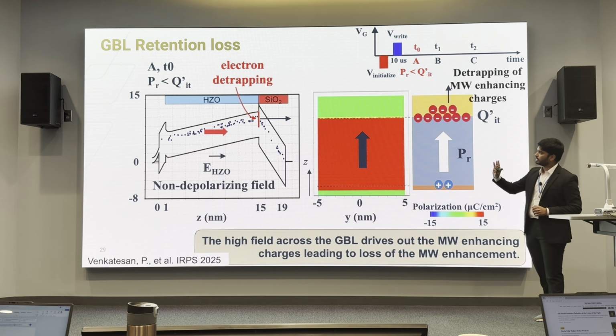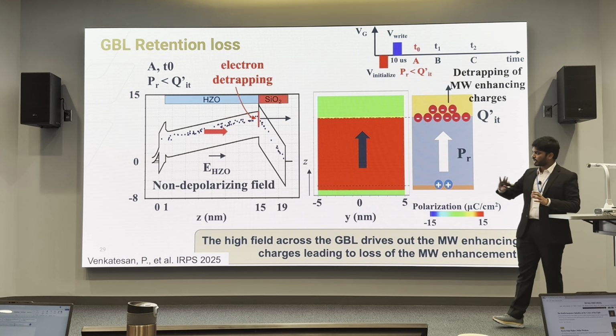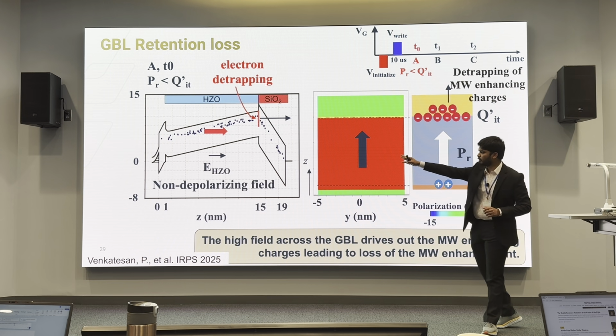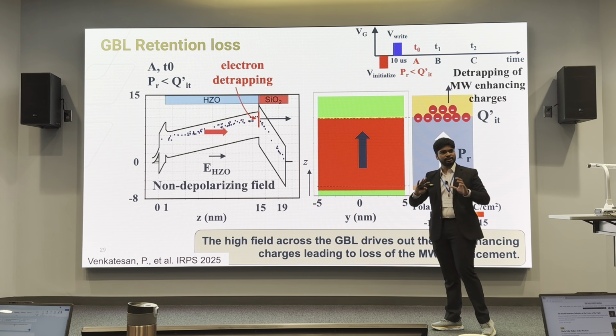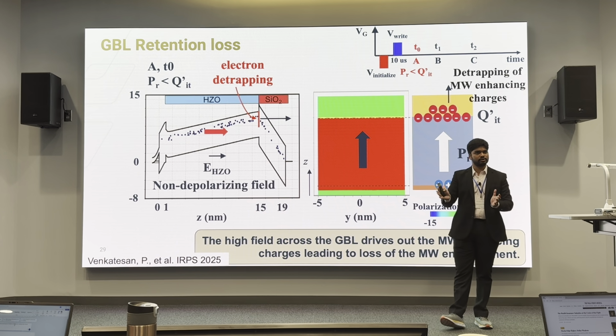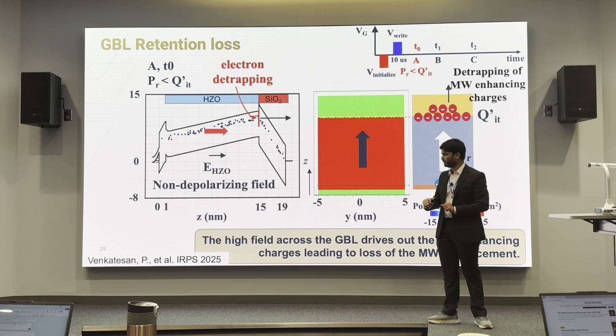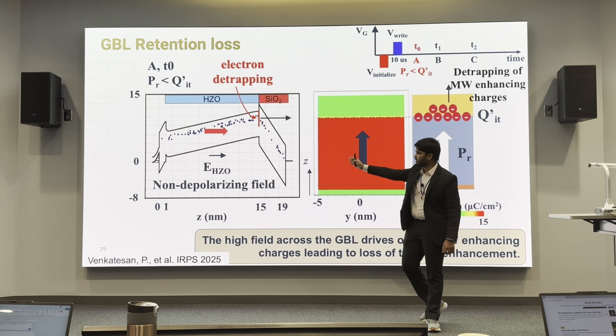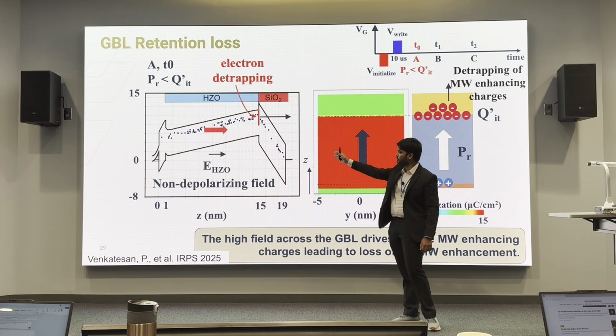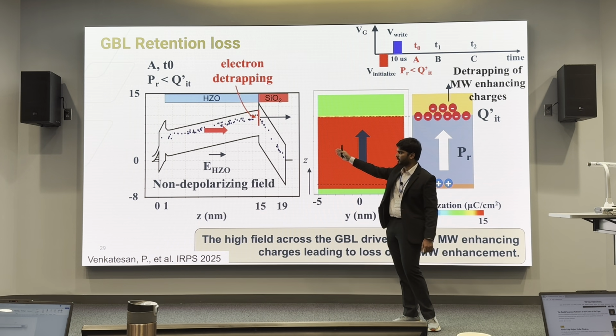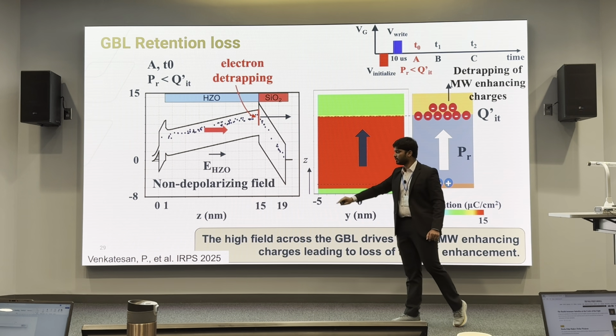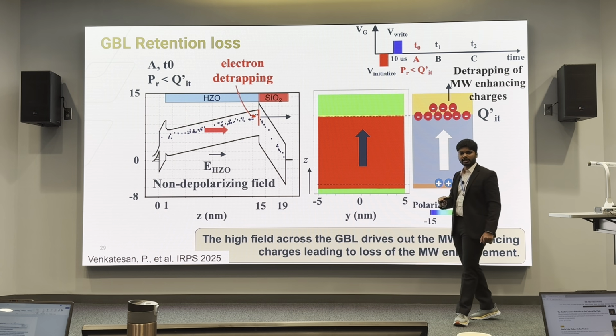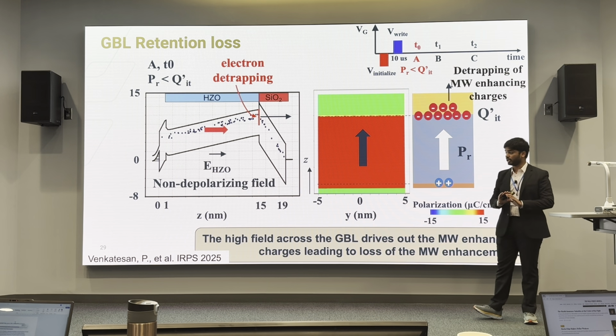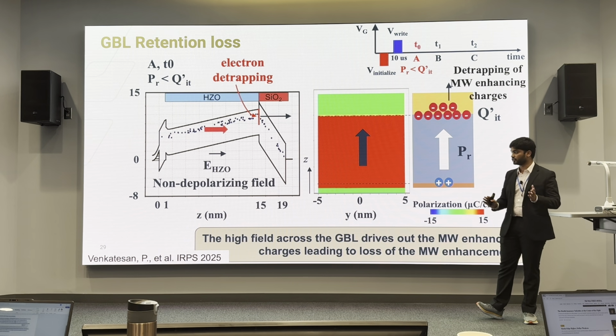So let's start with the gate blocking layer device. We programmed the gate blocking layer device. We have HZO and silicon dioxide here. I mentioned 2 concerns, depolarization and detrapping. So let's go one by one. In the overcompensated state, where we have Q_IT prime, which is the trapped charge at the interface, greater than the polarization, the field along the ferroelectric layer is non-depolarizing, so no depolarization, which is great.